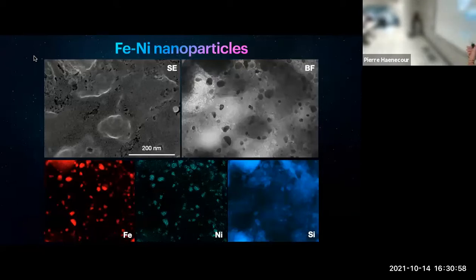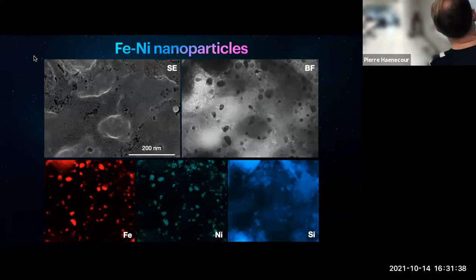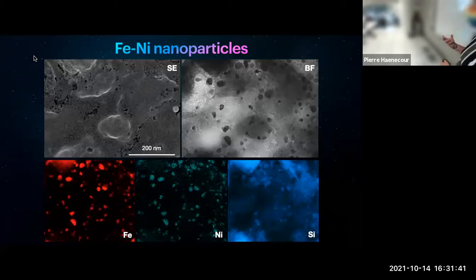If we look at the elemental maps afterwards, you can see an iron nickel particle, clearly with some silicon in it. If you look at the texture in secondary electrons, showing you the surface, you can see clear morphology of material melting and going away. There are vesicles going out, and nanoparticles that even reach the surface, all around. There is exsolution: for example, a nanoparticle that shows clear exsolution with different concentrations of iron. You can see on the elemental map there is way more iron on this side. There is a lot happening, and some of them have a clear euhedral shape, showing that it's a nice crystalline metal core.